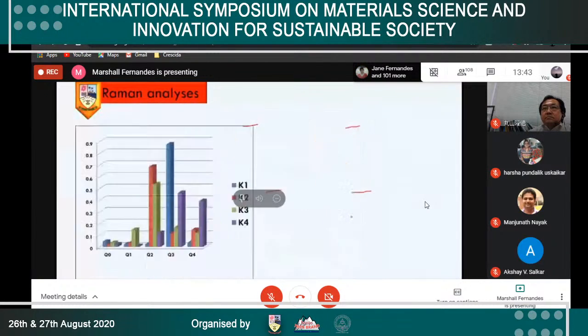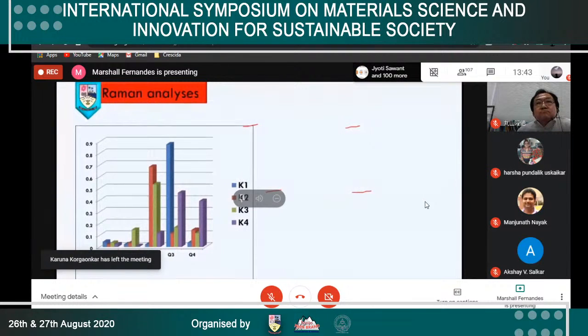For better understanding, the fractional Qn areas were determined and plotted against the percentage area contribution to the Gaussian fits. So what we observe here is that the sample K1, which is without iron, has a large contribution due to the Q3 unit, but on introduction of iron, the K2 and K3 samples show higher numbers of Q2 connectivities, and the K4 sample shows Q3 and Q4 type connectivities. Hence, addition of iron has surprisingly caused the structure of K2 and K3 to be more of an open type.